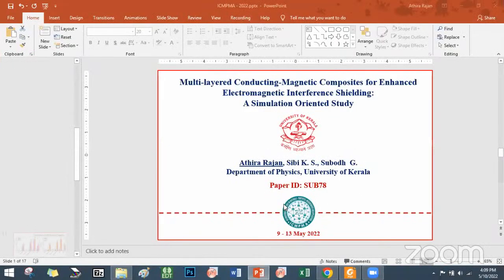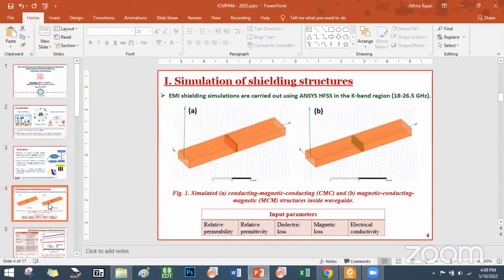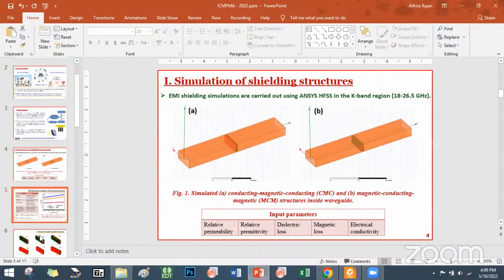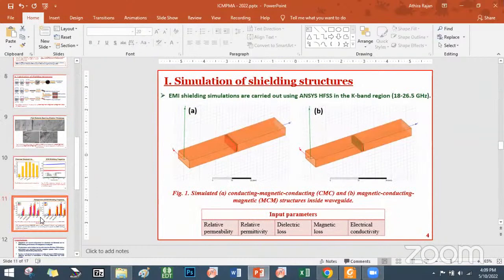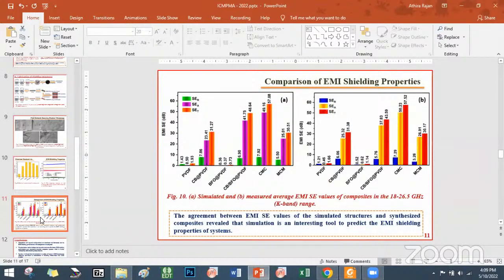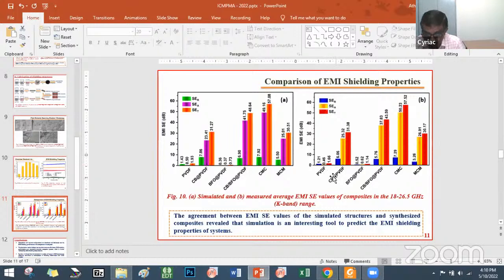So, you are confident about the accuracy of your simulation? Yes, sir, I'm confident, because in order to test whether our theory works or not, we first started with PVDF, which is a simple composite with no fillers in it. We tested it in our lab from 18 to 26 gigahertz, in the K-band region, using the waveguide measurement method. It is found to be very much matching: in the simulation it is 1.93, and in the measurement it is 1.66 only, which is a well matching result.